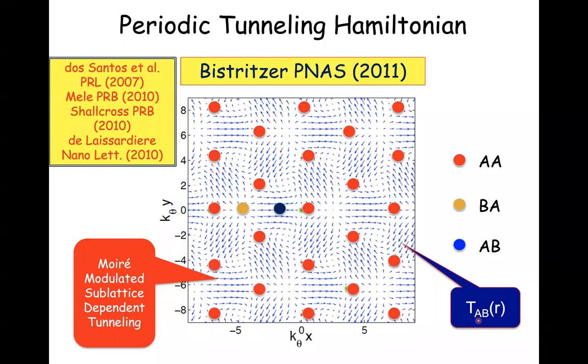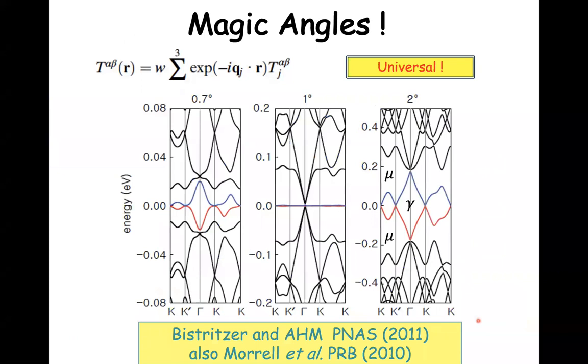So in this way, you can have a model Hamiltonian. And the magic thing that happened, which we didn't try very hard to understand and didn't really fully understand at the time, is that at a discrete set of twist angles, the lowest energy states go extremely flat. The velocity of the electrons at zero energy goes through 0. And the typical velocity of electrons in these bands is reduced by a factor of more than 100 relative to the electron velocity in graphene sheets.